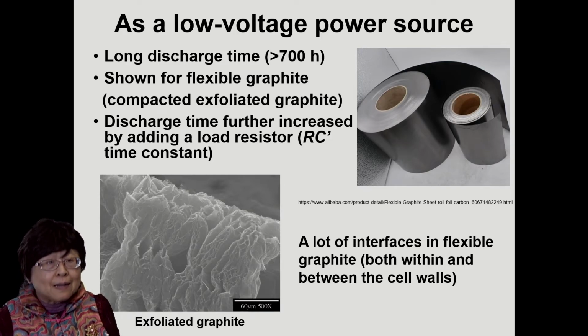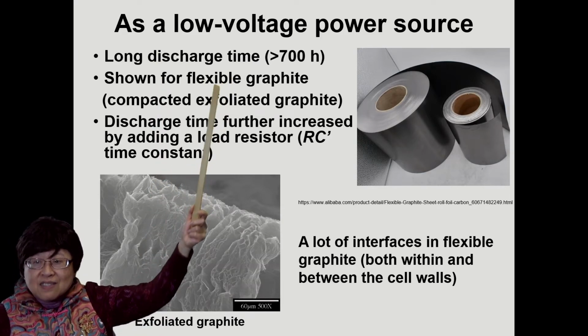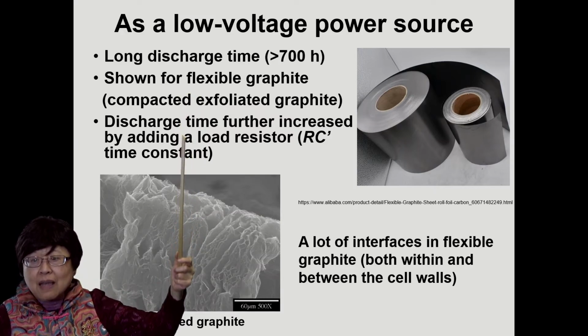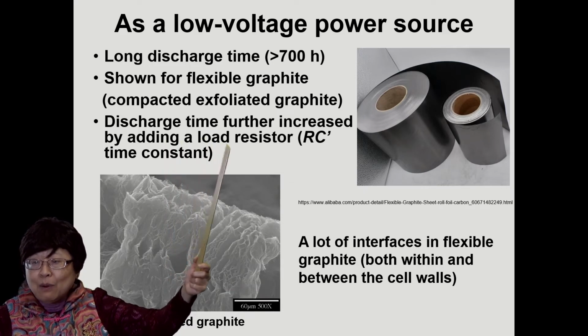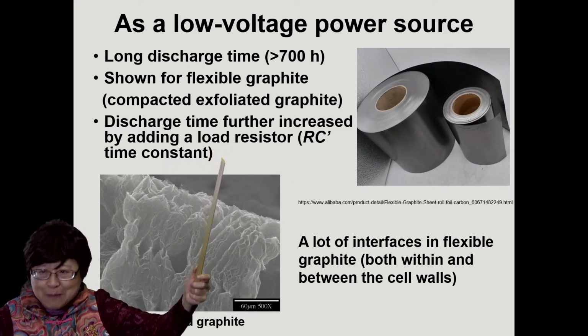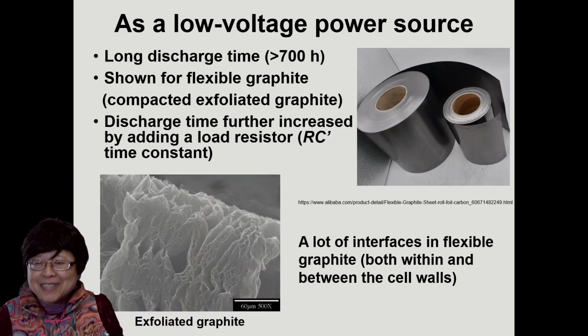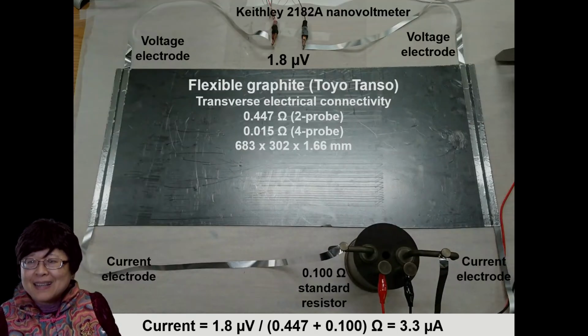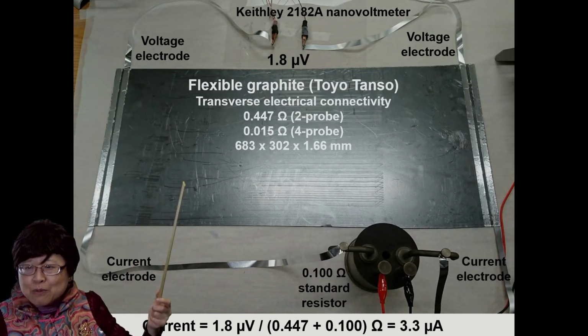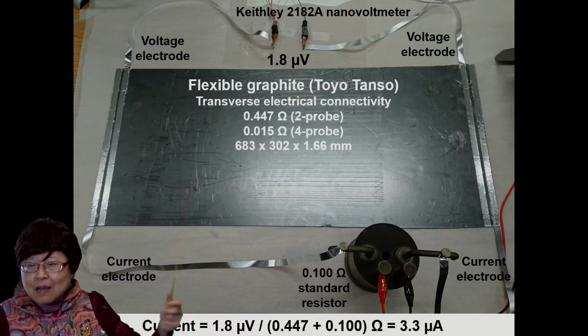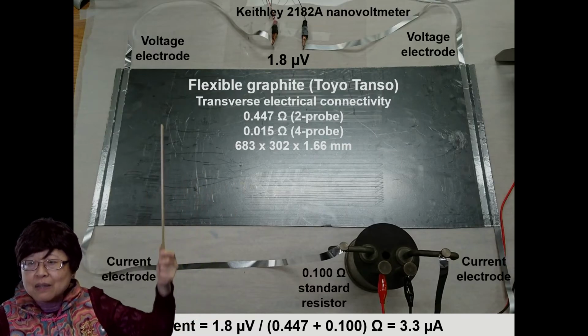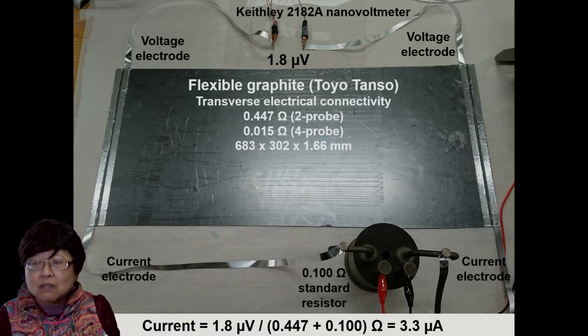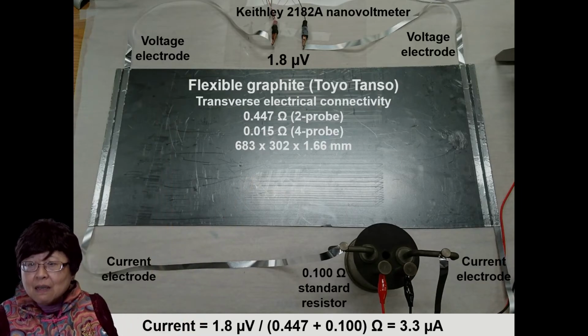be very strong in the electric behavior in the sense that it doesn't discharge easily. And we have a discharge time greater than 700 hours. Okay? And we can further increase this discharge time by adding a load resistor. Again, RC time constant. Having more R would increase the discharge time. And this is our piece of flexible graphite. And it is two-dimensionally isotropic, so there's transverse as well as longitudinal electrical connectivity.